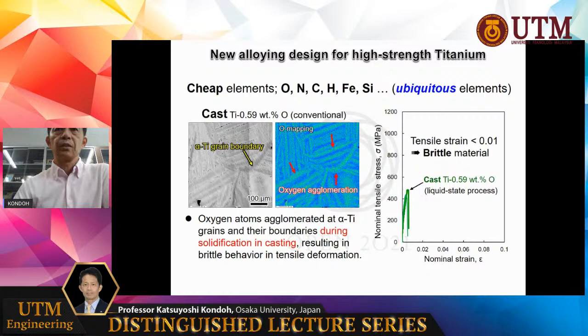For example, this is the tensile test result, shown in the stress strain curves of these cast materials. With the increase in strength, suddenly the strain decreases. That means breakage due to the brittle performance of a high concentration of oxygen atoms.